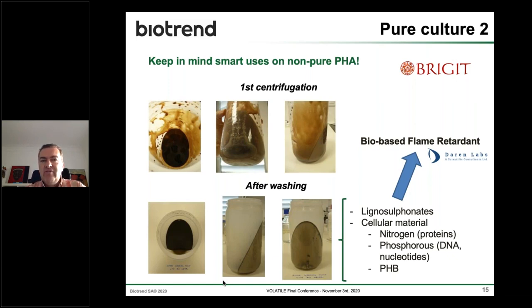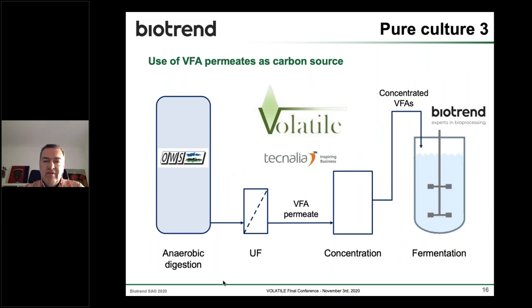Obviously, for this particular application, to have a very thorough purification would probably not be sustainable, both from an economical and environmental point of view. So we tried to figure out whether we could take the fact that we have these impurities to our benefit, and together with a partner in the project, we found out that this kind of composite material comprising PHA, lignosulfonates, and still some cellular material would be an extremely powerful flame retardant additive to plastics.